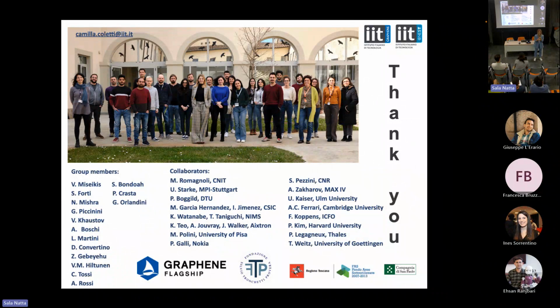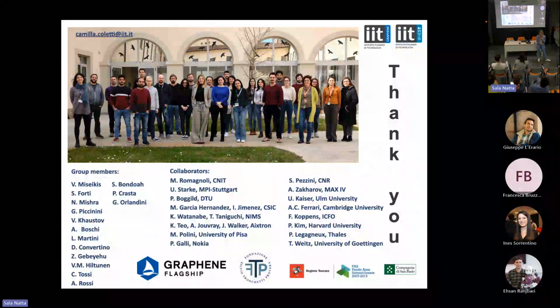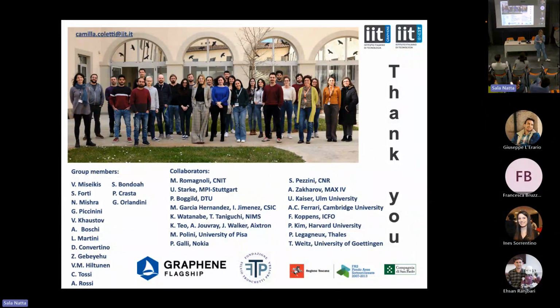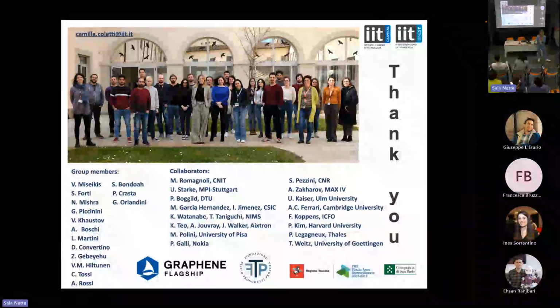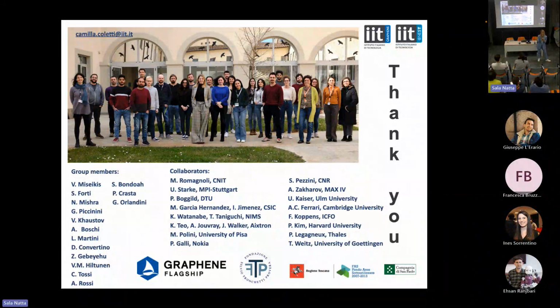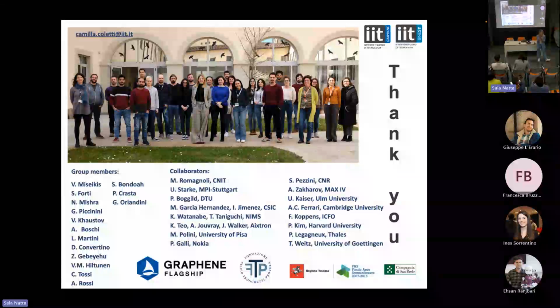When you transfer CVD graphene, the one I do, you can damage it because it's one layer. So when we did some coating for glasses, you go there and you scratch it, it's gone, right? You need to protect it. You can protect it with a transparent polymer. We do that very often for other applications where you need a conducting layer. When you need to substitute ITO or other conductive layers, you can do it with graphene very well. Then you can put just a thin transparent polymeric coating, and you have your function without damaging the graphene.